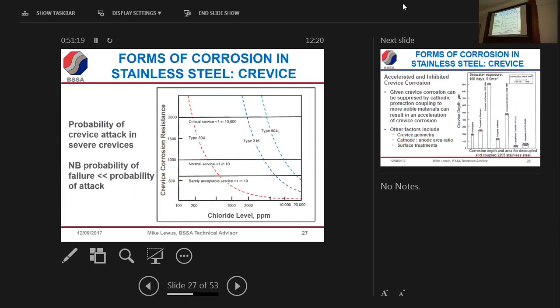Something showing a similar sort of information, but it's really just picking out 304 and 316 and 904L, which are probably the big three you might want to consider. You can almost certainly rule out 304 if you don't want the risk of pitting. I've been talking a lot about the marine atmosphere, not subsea. So we usually rule out 304. Type 316, yes, it can tolerate the atmosphere, but keep an eye on it and clean it down and wash it. Type 904L is much more resistant to crevice corrosion attack. You can see this is crevice corrosion resistance and this is the chloride level. We can withstand a much higher chloride level with 904L.